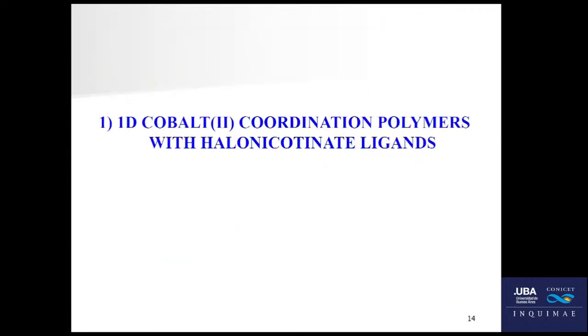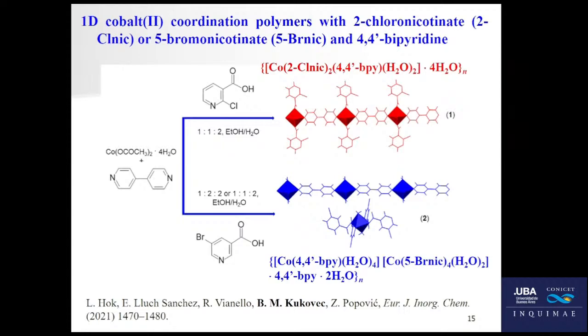Okay, so now I'm continuing with the first chapter: one-dimensional cobalt(II) coordination polymers with halonicotinate ligands. The synthetic route for these two compounds is shown here. We used cobalt acetate, the auxiliary 4,4'-bipyridine, and these two ligands, 2-chloronicotinic acid and 5-bromonicotinic acid. So the halogen atom is placed here in position 2 and here in position 5.